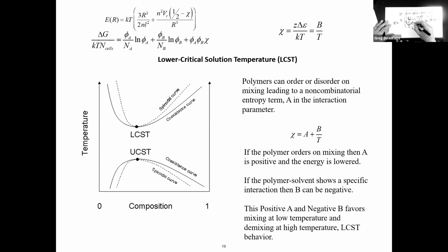That's called the spinodal region, so it will automatically degrade. If you're in here, it's actually within a smiley face, but it wants to phase separate to these 2 points, but it can't because it's already smiley. So small fluctuations will go back to the original composition. If you have a big fluctuation, it'll drive down to that point. That region is called the binodal. In the binodal region, in order to have phase separation, you have to have nucleation and growth. And in the spinodal, you have spinodal decomposition.